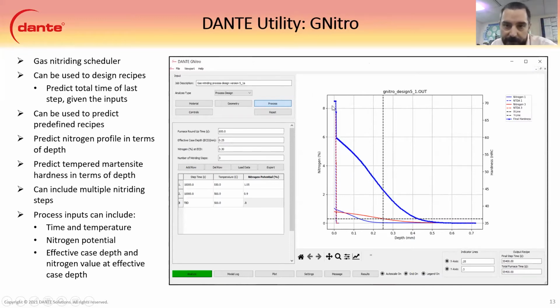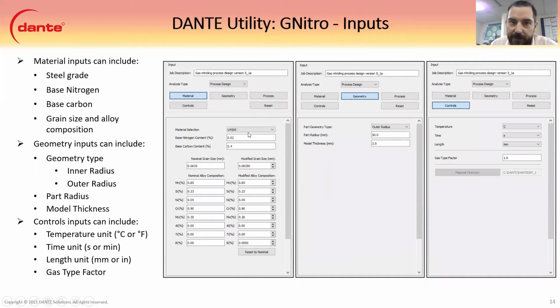The nitrogen profiles are usually more narrow or shallow. And you can see here, it actually has nitride information. So you can see that the nitrides are on the very near surface at the end of this process. And it works in pretty much the exact same way. We have material definitions based on the DANTE material database. We have geometry, and then we have units in the controls.